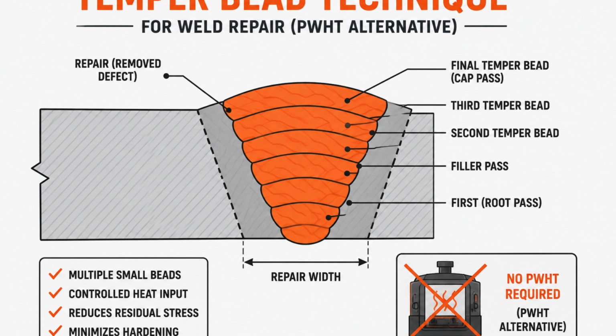Here's a field-relevant detail: if you find a defect after PWHT is already done, you don't automatically need to rerun the entire heat treatment cycle. For certain materials, UCS-56.7 allows a temper bead repair technique, controlled electrode size, preheat, and a final tempering weld layer that tempers the heat-affected zone as you weld, without a full furnace cycle.